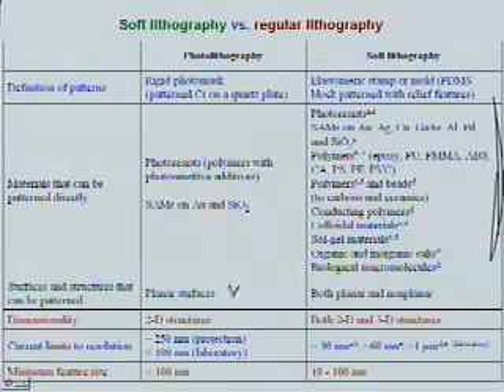It can be argued that this is a planar technology, while this one can be also three-dimensional. I don't buy this argument that much. In this case, you make two-dimensional structures. In this case, you make two-dimensional and three-dimensional. And then it can be argued that this one has a higher resolution. But this resolution comes at some price. While photolithography presently has about 250 in reality and 100 in laboratory features, soft lithography in laboratory conditions can go down to as small as 30 nanometers, with some strings attached to that. So the minimum feature size is essentially comparable. These people claim that soft lithography can be smaller in feature size, but again, that can be arguable.